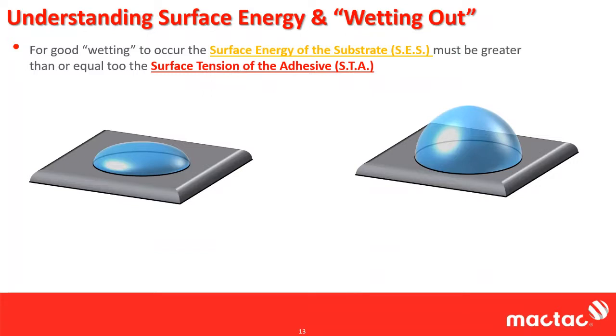So you might be wondering, how can I tell this without knowing what the materials are? Aside from the fact I wrote the presentation and I know the answer, if you ever see old coots like me visiting people, and we take a bottle of water and start spilling it on surfaces, or sometimes coffee, what we're actually doing is this. We can tell the surface energy of a material just by putting a few droplets of water and seeing what kind of bead is forming. We can't measure it precisely down to the dime, but we get an idea if something's polar, non-polar, or hydrophobic, hydrophilic, which is another way of saying that. We get an idea of what the surface energy is.